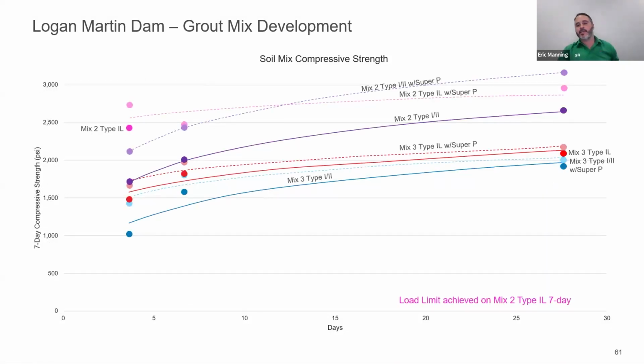I'll just highlight the high level results that we saw. We didn't really see any major changes, relative to the criteria we need for the grouting we're performing out there. We don't really need a lot of strength for the low mobility grout columns. Our design strength is 1500 PSI, and we were able to achieve that with replacing all of the fly ash and cement.